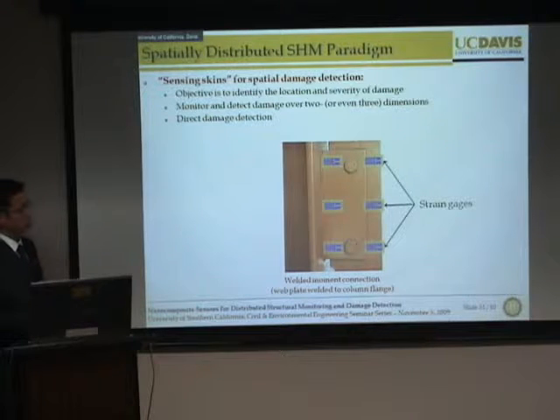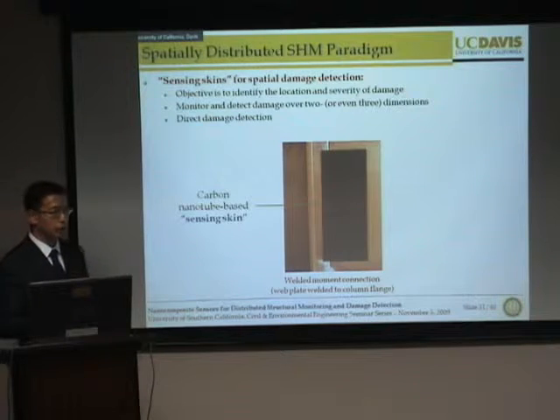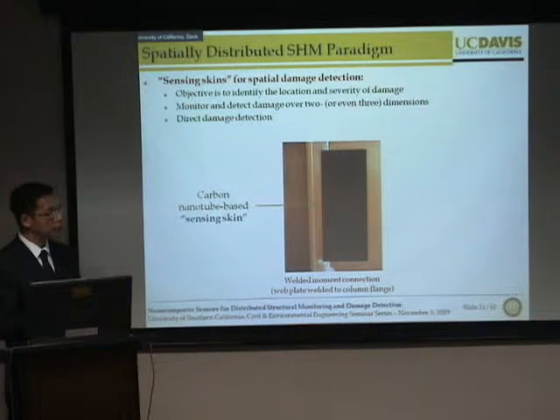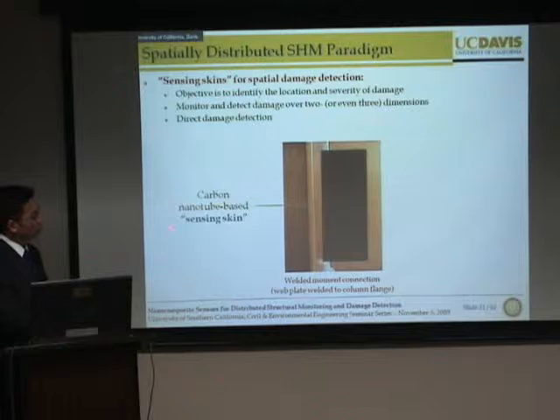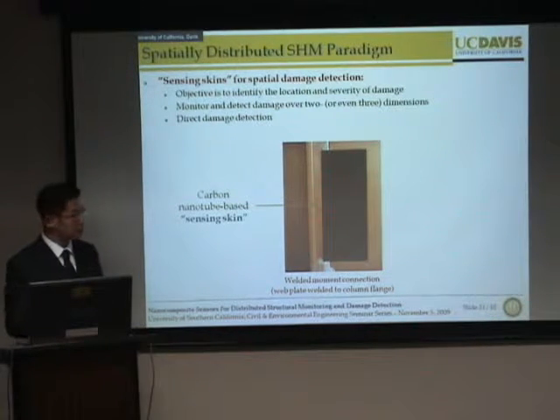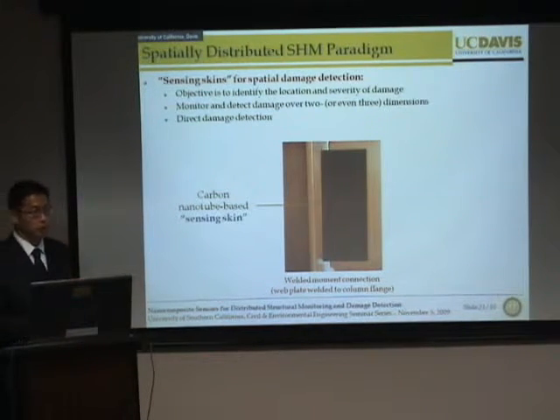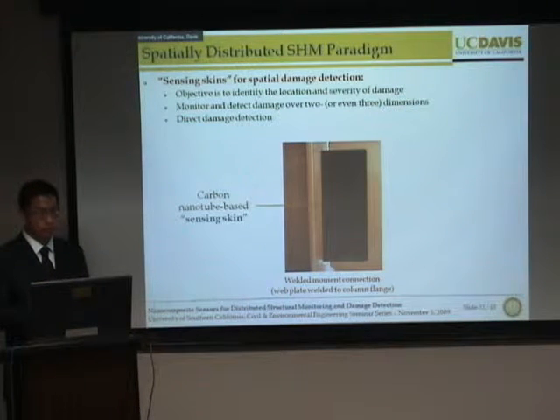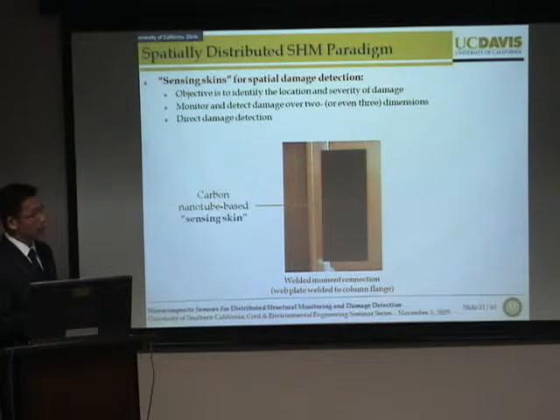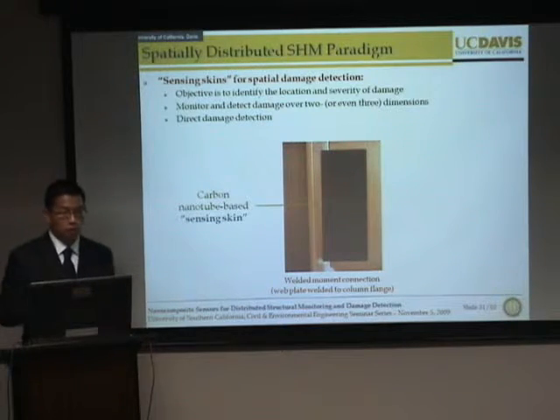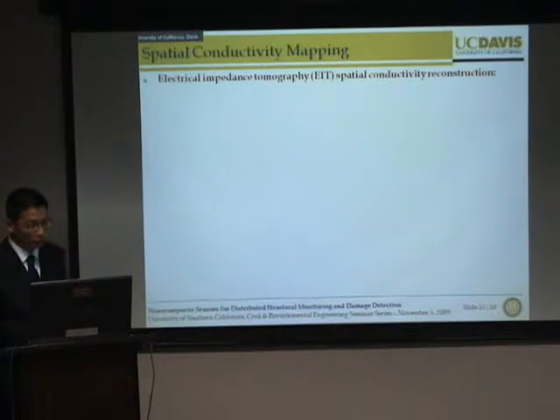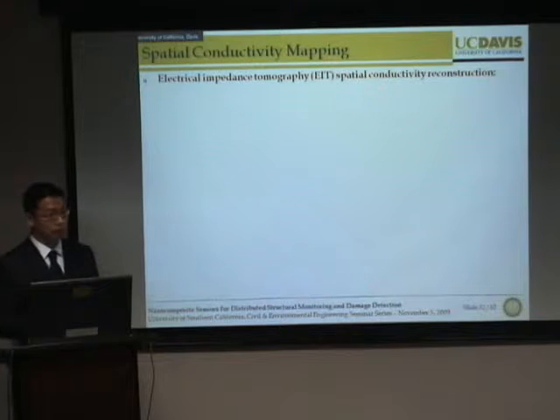Now, the objective of this part of the study is, instead of relying on distributed sensors, we want to come up with a material that is sensitive to damage at every location. That is, we want to deposit what's known as our carbon nanotube-based sensing skin onto the entire welded moment connection, so that we can directly measure strain or other damage features directly, but also to identify damage location precisely. Now, in order to achieve this goal of spatial damage detection, we've coupled our thin films with a technique known as electrical impedance tomography spatial conductivity mapping reconstruction.